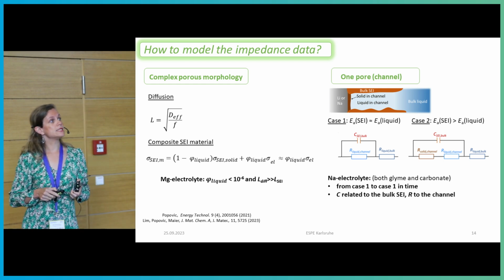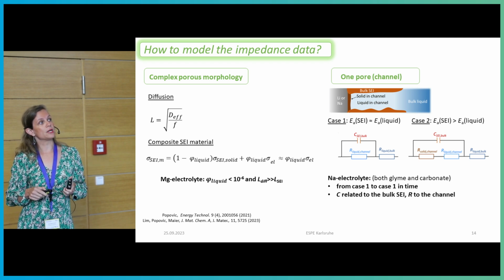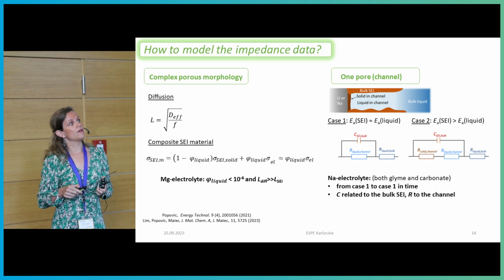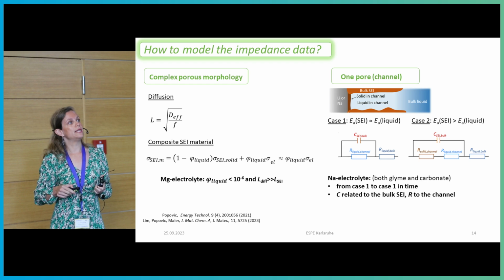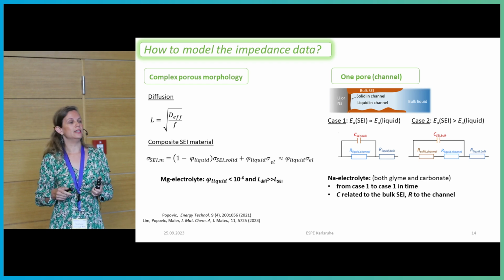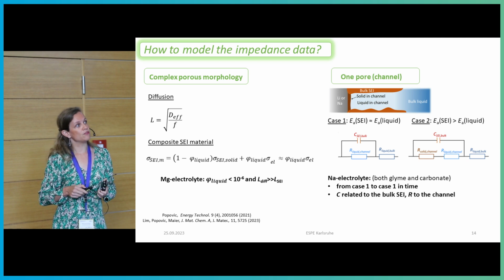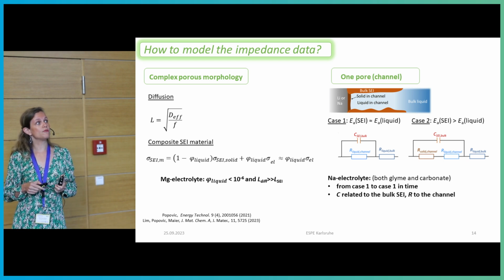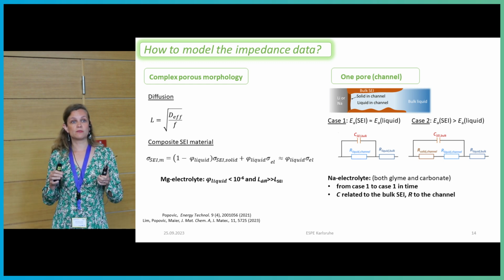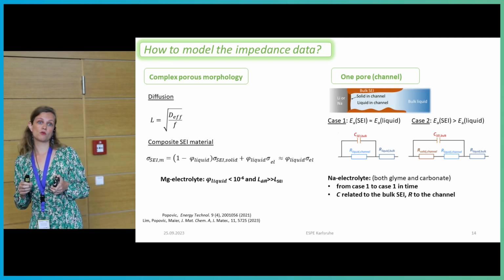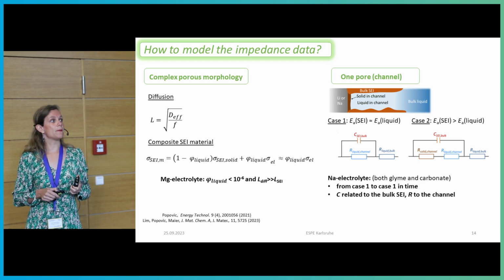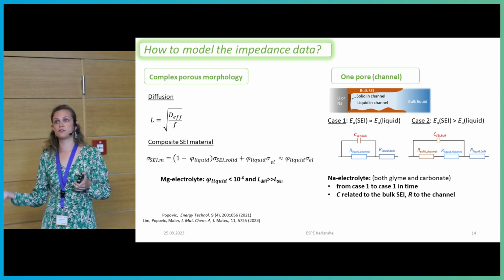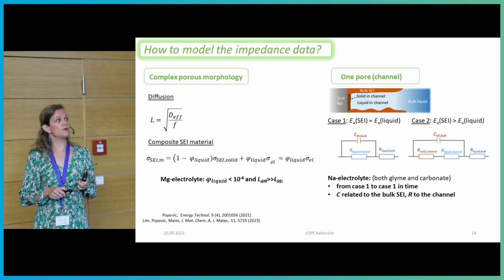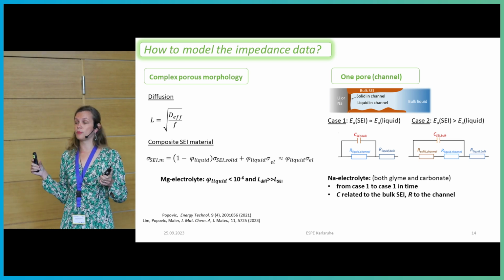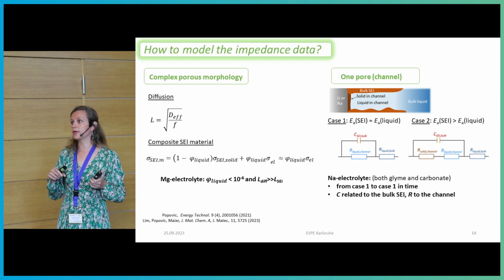And in the sodium case, both in the glyme and carbonate electrolytes, we see that we have this situation where we have highly porous dominant liquid pathways that then become something in between liquid and solid in time. If we build these kind of equivalent circuits, what's really important to see from it, and that is what has been confusing for the impedance community for a really long time, is that the capacitance that we get from those semicircles in the medium frequency range are actually related to the bulk, so to the solid state part of the SEI, while the resistances are related to the channel.